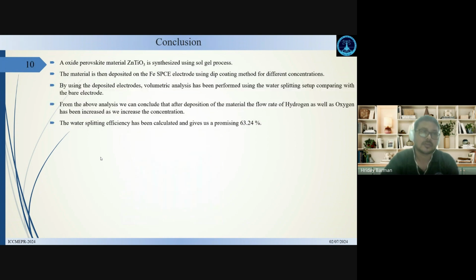So we can conclude from this analysis that first we have an oxide perovskite material, zinc titanate, synthesized using the sol-gel process. Then the material is deposited on the iron screen-printed carbon electrode using the dip coating method for different concentrations. So by using the deposited electrodes, volumetric analysis has been performed using the water splitting setup, comparing with the bare electrode. And we are getting that after deposition of the material, the flow rate of hydrogen as well as oxygen has increased as we increase the concentration. And the water splitting efficiency has been calculated and gives us a promising 63.24%.